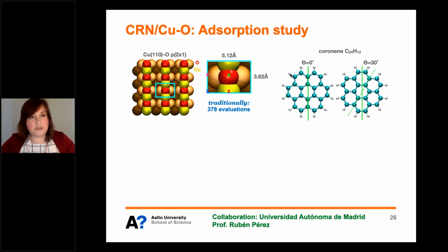So the way you traditionally do this is you find the smallest part of the surface that repeats itself. This is shown in the blue rectangle, and then you find some typical symmetry points where you want to put the molecule on, and then you relax all degrees of freedom and find which is the preferred adsorption site, and indeed it was copper. So Diego found this out in a traditional way using maybe 400 DFT calculations.